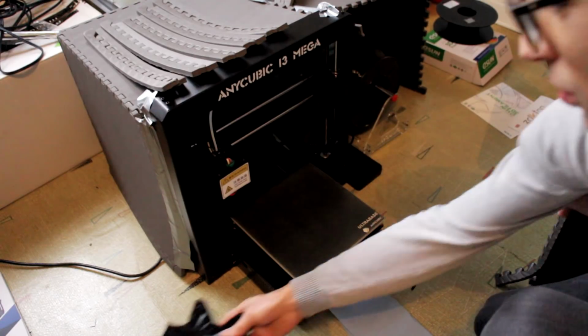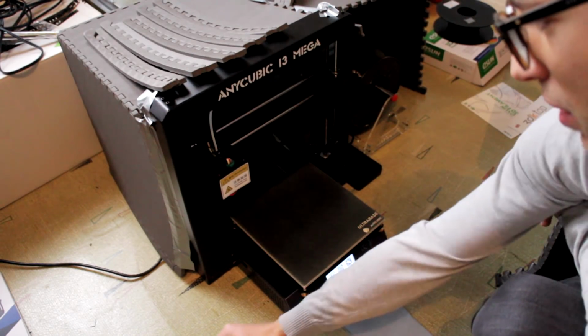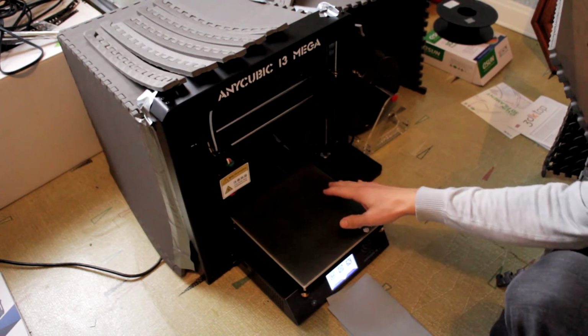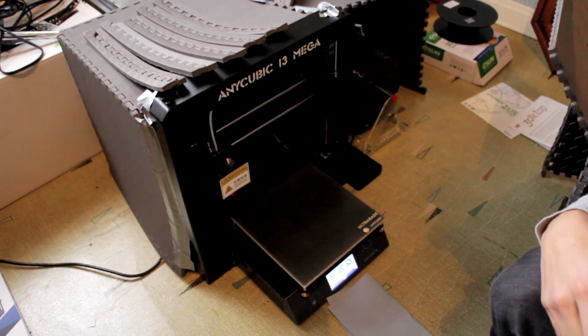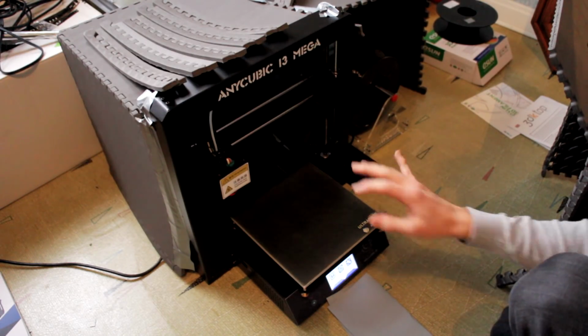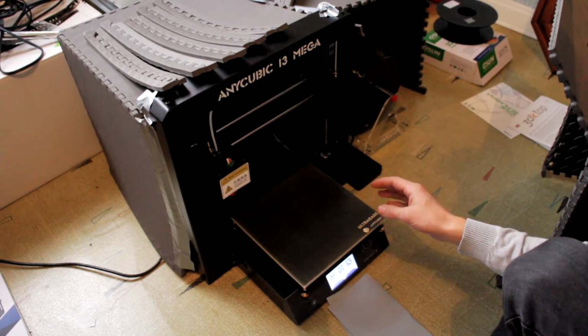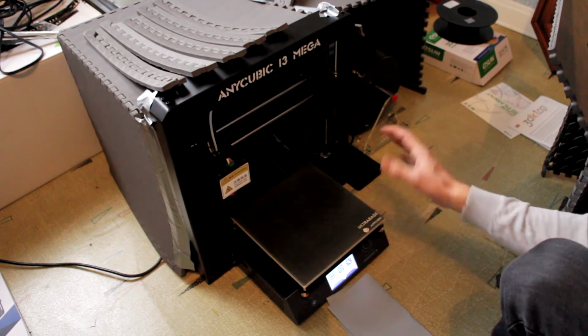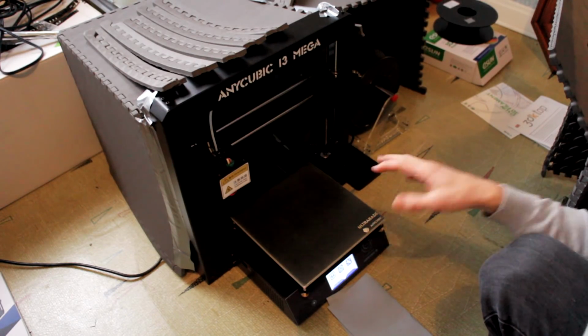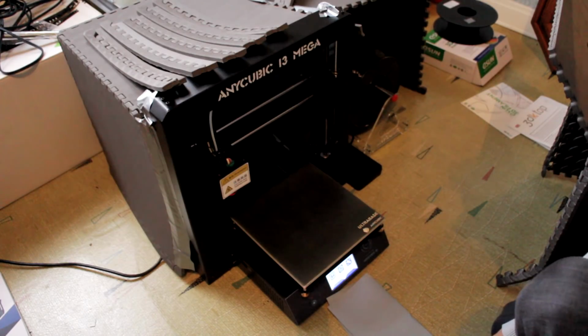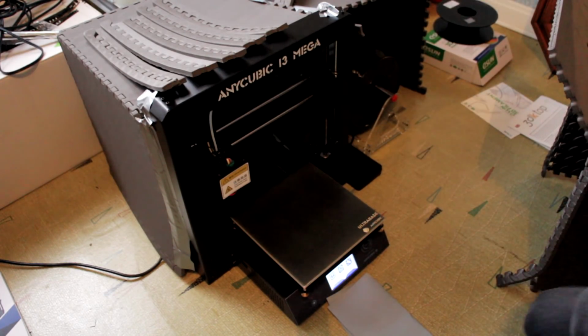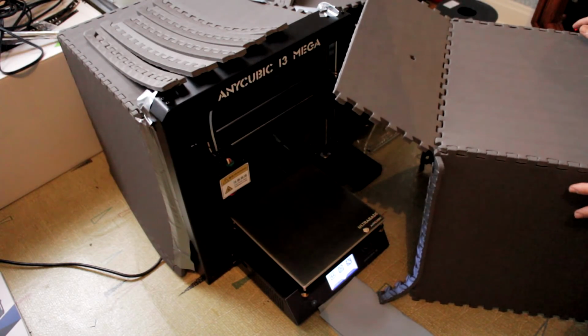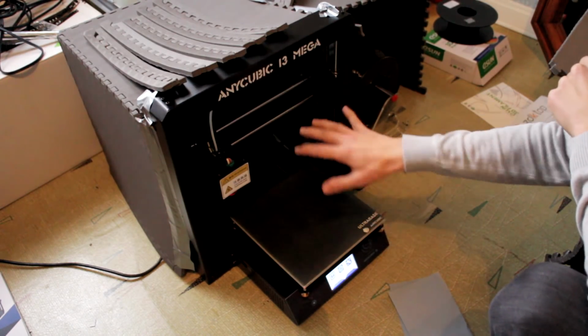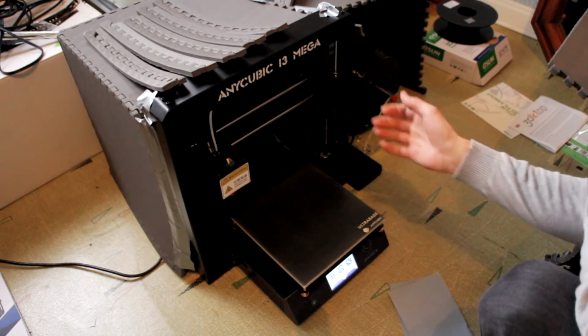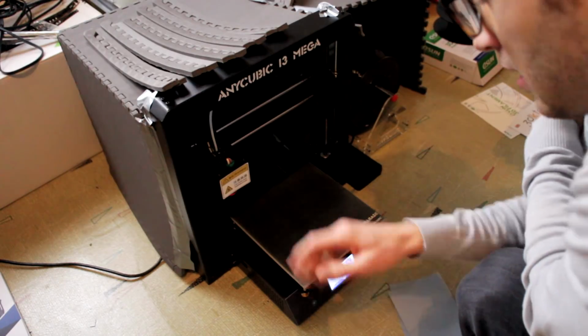After my first fiasco, I changed some settings. So now I'm printing on a hotter bed surface. So it's 90 degrees centigrade instead of 60 degrees centigrade. Also, I've changed from using 100% infill to 50% cubic infill, and I'm using 2mm walls, so in strength it doesn't change too much, but it uses a little bit less filament and there's a little bit less warping. Also, as you can see, I've built an enclosure, and I've used some of these foam floor tiles just to enclose the printer a bit, to keep the temperature a bit more stable in here, so that there aren't too many temperature fluctuations. And I've printed the first one.